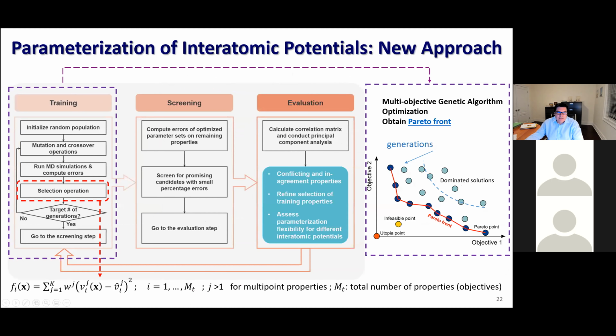So the training goes with the use of a multi-objective genetic algorithm of optimization. And we do the optimization by obviously having initial conditions and then evaluating with MD all the properties. And then we have a fitness defined by this expression here. And the fitness is for each property. So the properties go from 1 to MT in this notation. So you have, let's say, a stress strain curve, dissociation, elastic constant, all those are properties. Can be single quantities like energies, for instance, cohesive energy, or could be a stress strain curve with many points. So we use this notation J here to run over all the points in the case of multi-point properties.